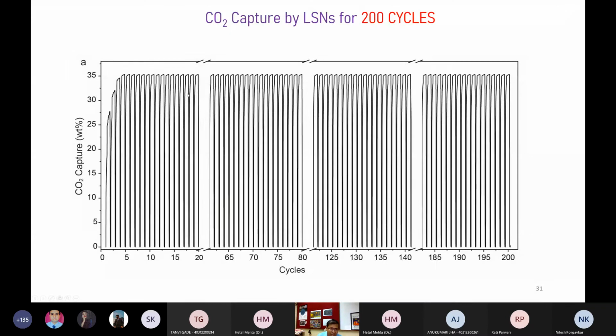We showed that one can capture the CO2. At least we tried up to 200 cycles, which means around 100 days or maybe 150 days. It takes around 12 hours or more to have one complete experiment.